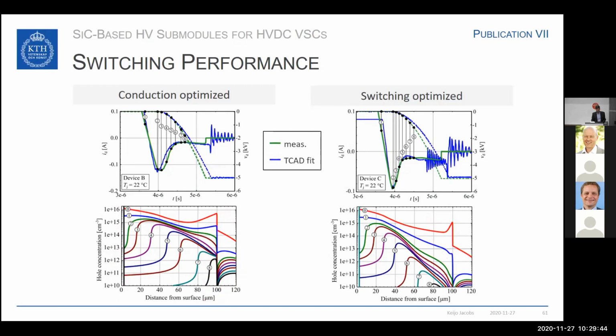This also has the side effect that we have charges trapped here at around 80 micrometers, and this leads to a snappy turn-off of the diode, as indicated in the measurement by these oscillations here. You can also see a bigger oscillation afterwards. That one is due to the commutation of the diodes and is related to the inductance of the circuit.